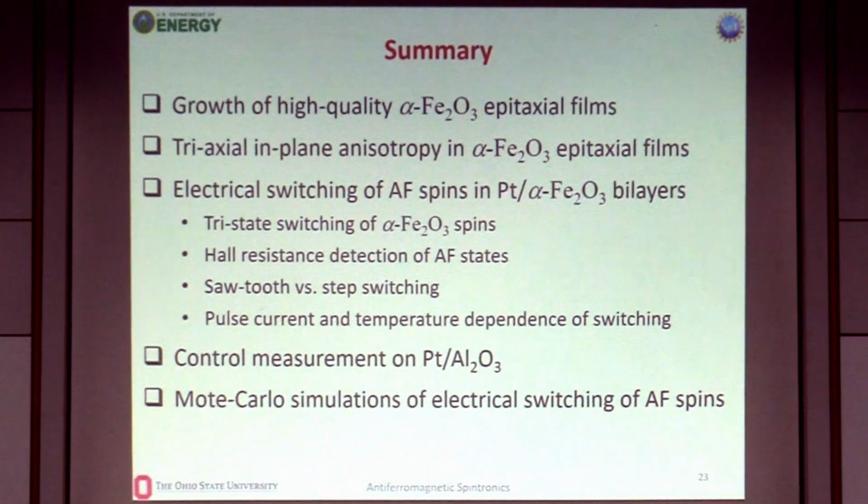So 2 questions. The first one is you said for the 30 nanometer film, you did not see any magnetic moment. However, we would expect that. Actually, I should take that back. My student did a more careful measurement because of the large slope. There seems to be a loop in the middle, but at high field it's a pretty weird shape. So there should be something in there, although we were not sure. So we grew a thicker one, and that's also a cleaner moment. That agrees with both. And the second question I have is how the thickness depends on the switching.